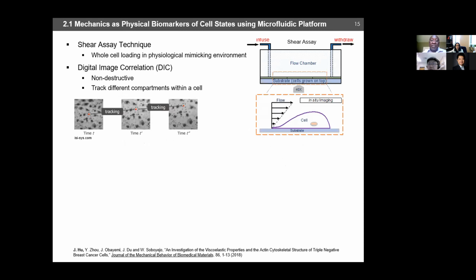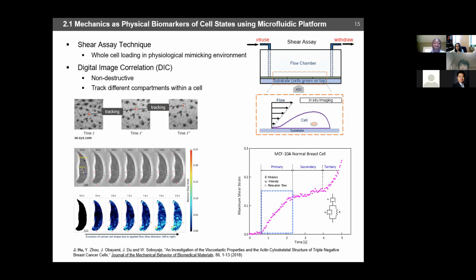Now we can go one step further by looking at the shear deformation of the cells. And if you look at the flow of the fluid over the cells, what you find, of course, is that you induce local displacements due to creep deformation phenomena that are associated with the applied shear stresses. So using digital image correlation, one can now map the displacements, and from the displacements, you can map the strains as a function of time. And this is from the work of Jingji when she was a PhD student.